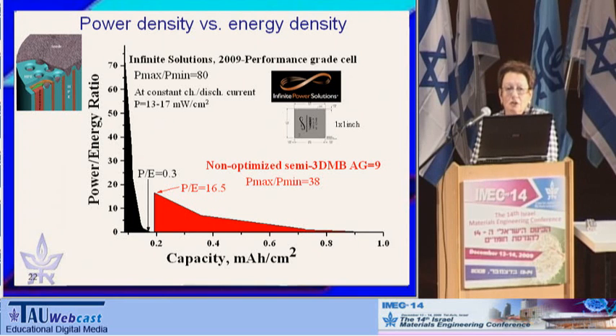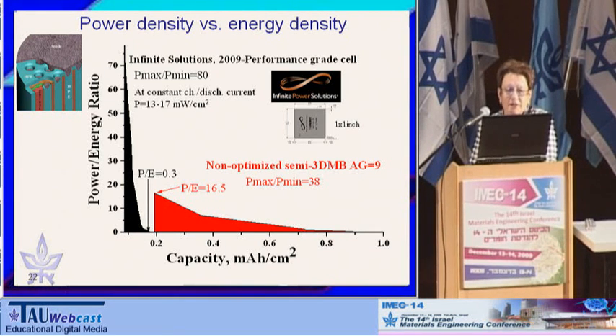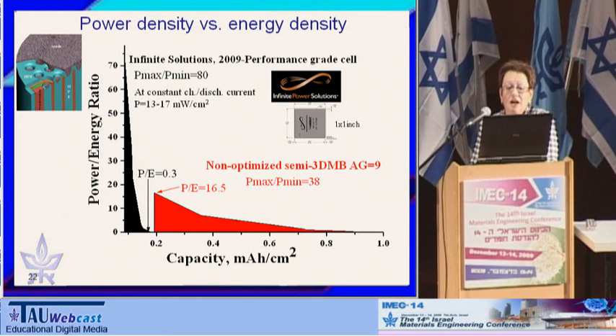And I can say, unfortunately, that these values are something about 3 times higher than the values achieved by our system so far. However, when the capacity of this state-of-the-art planar all-solid-state battery, the area of which, by the way, is 1 by 1 inch, is doubled, the power drops by a factor of 60 to 80. In our non-optimized semi-three-dimensional microbattery, increase of the capacity by a factor of 5 is also followed by the decrease of the power capability. However, this decrease is only by a factor of 20 to 40.